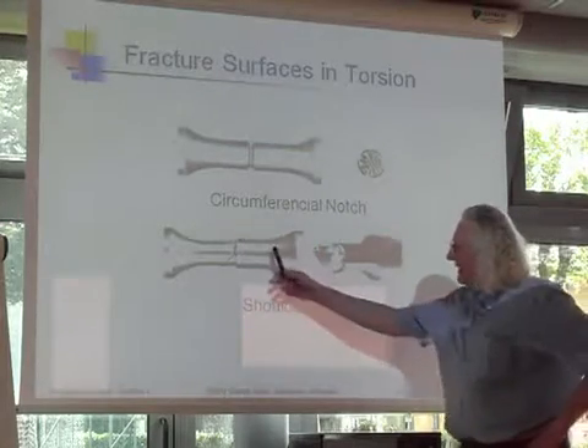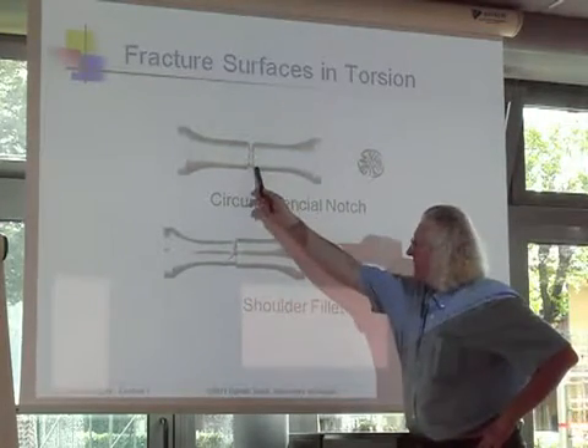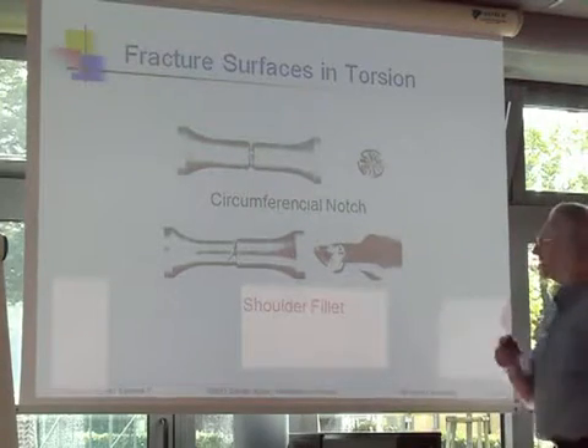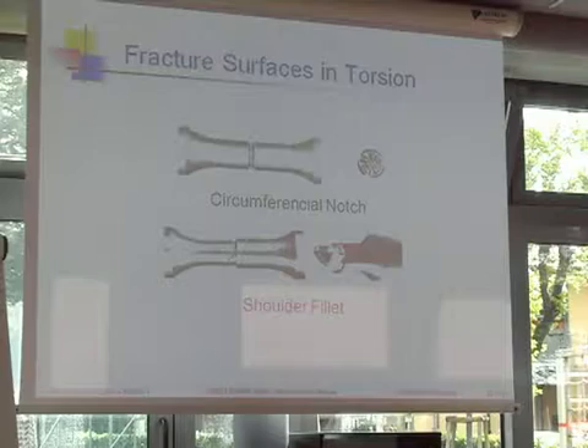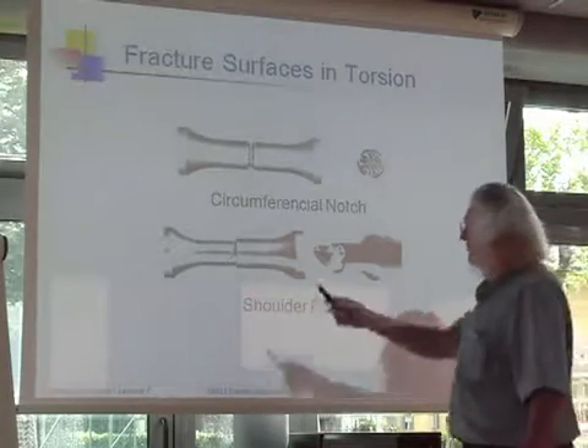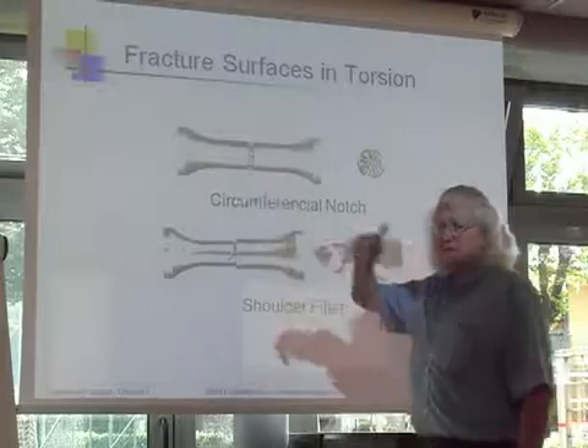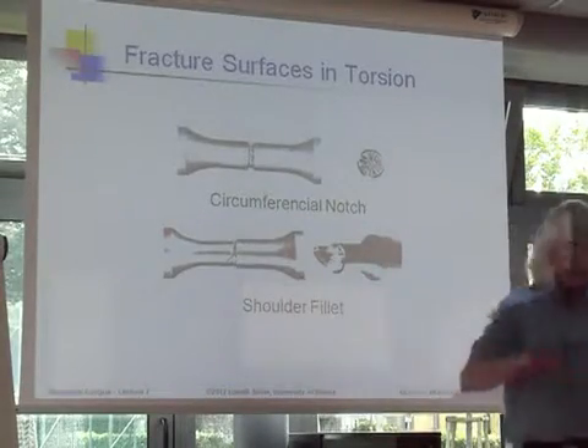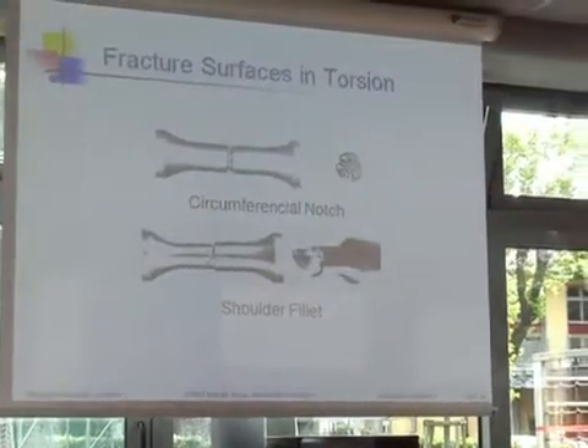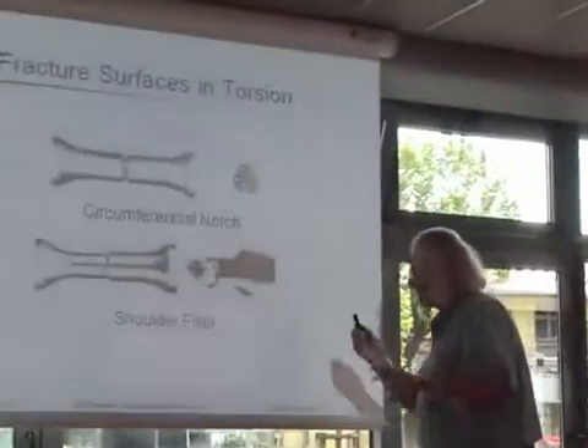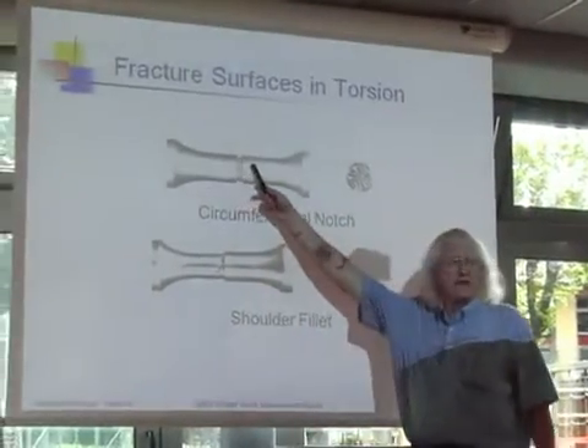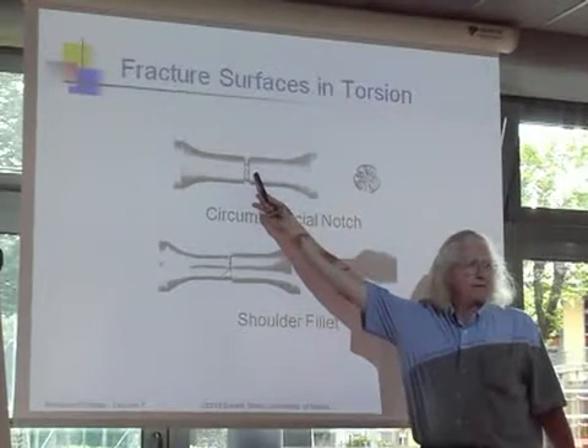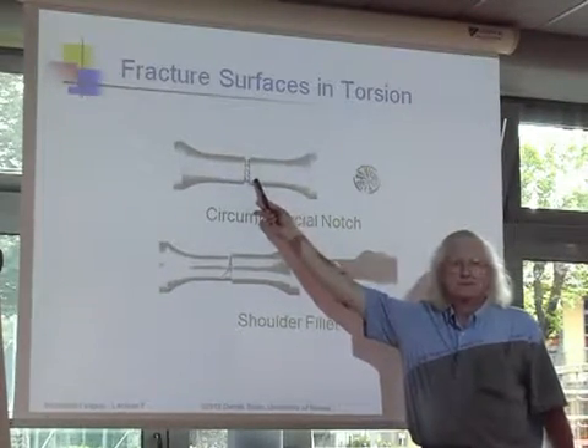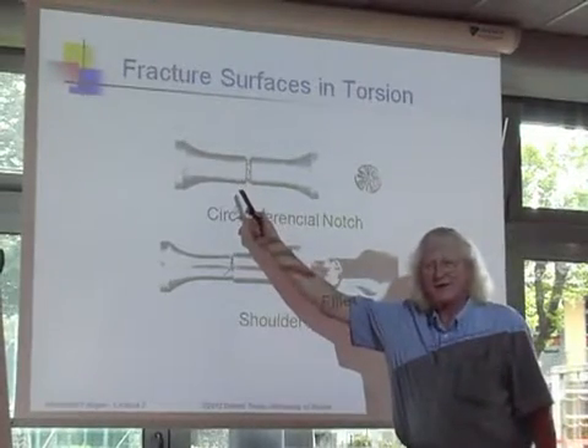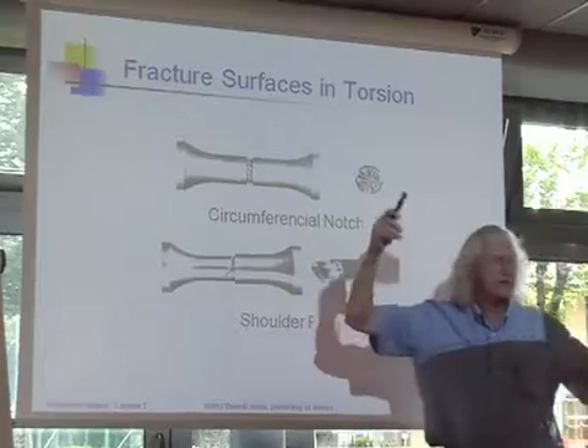We can either look at something that has a step shaft like this, or we can look at something that has a groove around the edge. And okay, I have my view of fatigue, and I have my calculations, and I calculate what happens at the root of the notch there, or I can calculate what happens here. And if it's a long life fatigue problem, then I showed you yesterday that these are these spiral cracks. But what happens when you start to get these long life spiral cracks in this situation? The cracks grow out of the stress concentrator. Of course, if the cracks grow out of the stress concentrator, they're not going to go very fast at all. And the lives are really, really long.